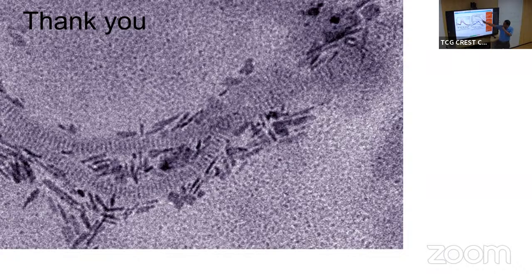The third one, what you are suggesting, you can even take it on the hot plate and heat it. You'll see the ligands will melt and the nanorods will coalesce. But that coalescence will be uncontrolled. It's not like two-dimensional. Maybe they'll form two-dimensional islands, small islands, but it won't be a large area two-dimensional.